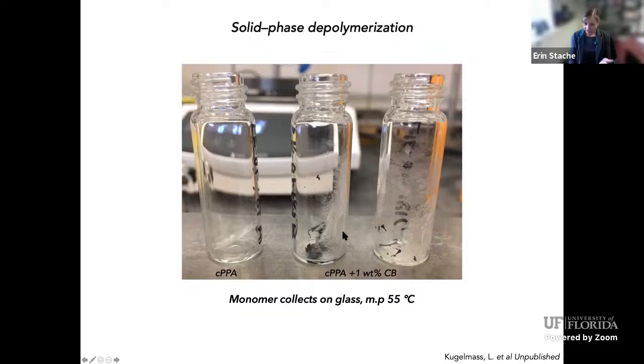And so these are what they look like in practice. So this film on the left here is the film without carbon black in it. You can see it's pretty much unchanged. It still has its structure. It hasn't melted. It's not yellow. And then when there's carbon black, these are cast from 2 different solvents. You can see that as it depolymerizes, the monomer actually is melting and sublimating onto the surface of the glass. So we could actually collect this and repolymerize it, most likely if we wanted to, just something we're still working on. But you see the film is pretty much completely disintegrated.